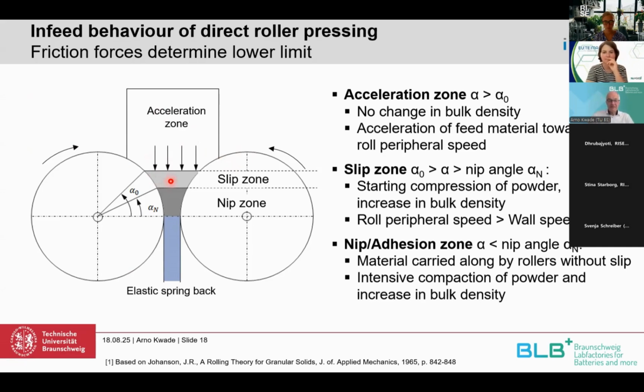Slip zone means that there are still some speed differences between the powder and the roller. And then we come to the nip zone, where the powder is really connected to the surface and there is no slip anymore. That means the powder is now taken into this gap and compressed, and then you form the film and get the elastic spring back.